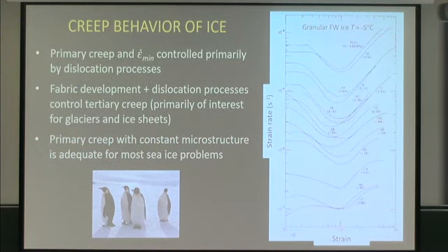So freshwater ice, because I had a good set of creep results, just to give you an idea what's going on. So this is a log plot of strain rate versus log strain for increasing stress levels in all about the same 1 millimeter grain size. What this shows you is that in general, sea ice more or less does this. There's primary creep up to this minimum. That's what Glen's law describes. It doesn't tell you anything about before and after. It just gives you a relationship between strain rate and stress, in fact, for that minimum creep rate. My model, if you play the whole thing, will give you the whole curve. I'm not going to get into the fabric development that produces this, but it does handle that quite nicely.